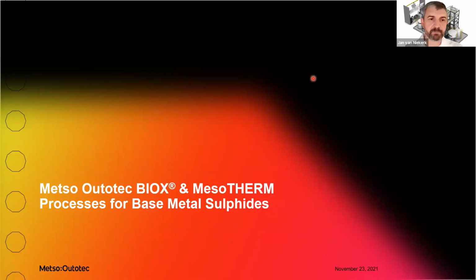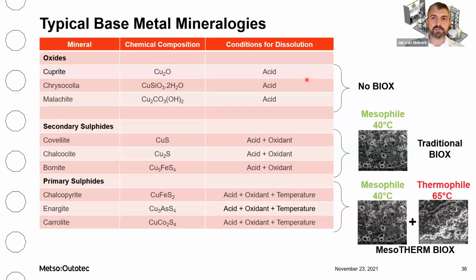Yep. It's a quick thing. Now, as I said, the BIOX process and the mesotherm process can also be used for the treatment of base metal sulphides to recover copper or cobalt. If we look at typical copper mineralogies, your oxides will be leached using acid, so no real BIOX needed there. For your secondary sulphides, the covellite, chalcocite, and bornite, you'll typically use your 40-degree or mesophile BIOX bacteria.